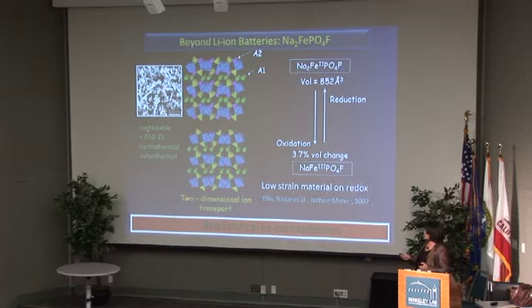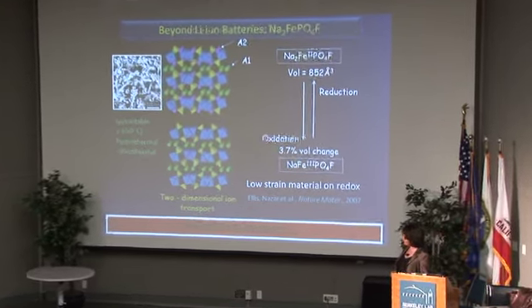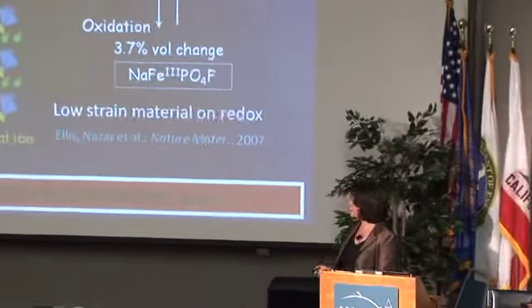This material also is metastable. It falls apart at less than 650, so we have to make it either by hydrothermal or solvothermal processes, because solid-state reactions, despite what the patent says, don't get you there, because it can't be made at 700 under ceramic conditions. So we were hoping that this would be a new family of sodium-ion conductors. It turns out that getting sodium-ion conductors to work well is very difficult, because sodium is just a little larger than lithium, and so in most cases the volume expansion on taking out the sodium, or vice versa, putting it in, is enough to cause enough strain in the material to result in really poor kinetics. So we were kind of lucky with this material because of this process of the so-called pillaring, and we're hoping to find other materials that behave similarly.